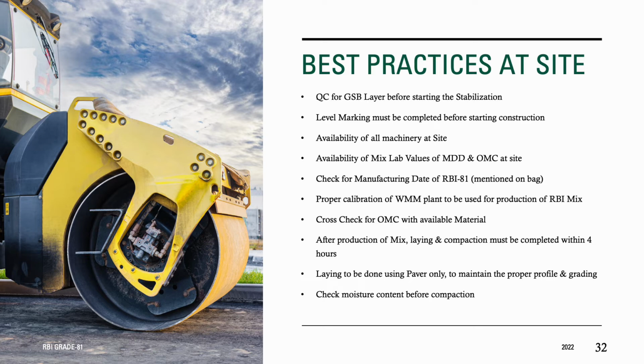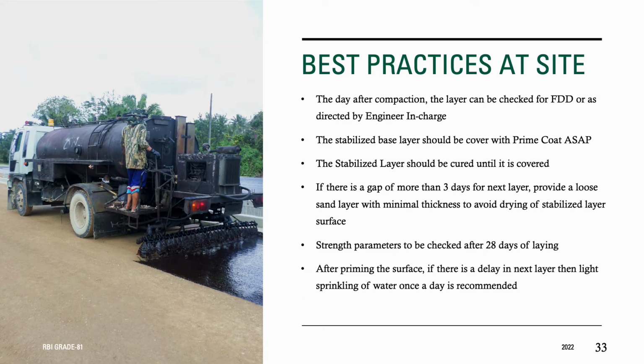The compacted layer, after it has been initially set, should be checked for its field dry density the next day. To prevent moisture loss, the stabilized layer should be covered with a prime coat, or in case of any delays, a loose sand layer may be laid over it. Strength tests should be performed only after 28 days of curing, since RBI Grade 81 is a cementitious material which gains the requisite strength by this time.